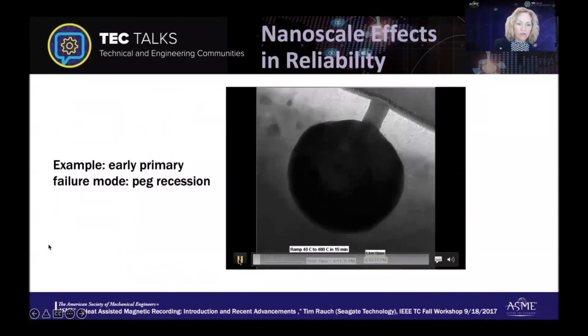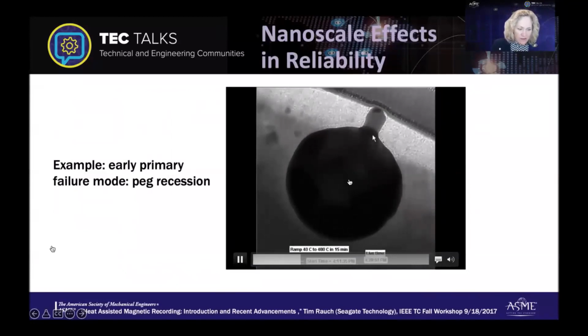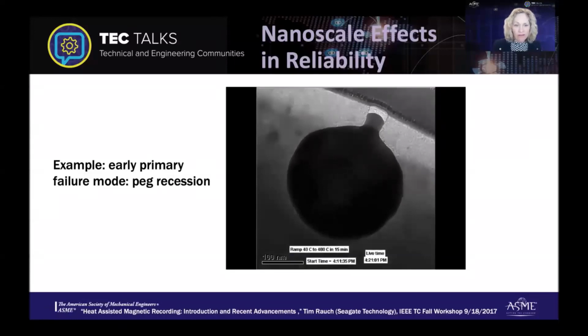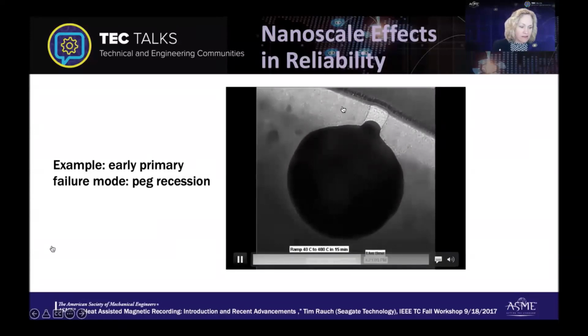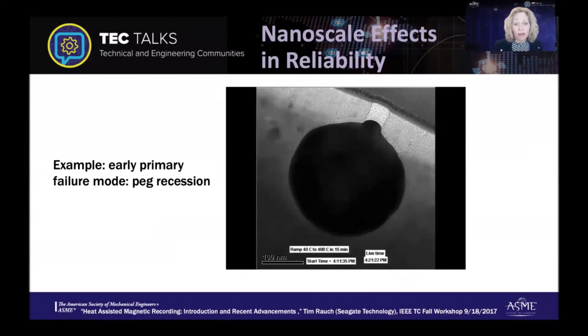We'll try that again. So you will see grains growing in the PEG, in the disc, and also the gold is densifying. And as the gold densifies, it wants to pull the PEG back into the disc. And you can see the PEG pulling away from the surface and being pulled into that disc. And because the surface plasmon effect is only a near field effect, once this PEG has retreated from the head surface, it is no longer within that tens of nanometers of the disc media, and the near field cannot reach the media anymore, and it fails to write any further. It's not heating that spot anymore. And this movie, really, with the tools of nanoscale technology, a transmission electron microscope, we are able to study this mechanism and come up with what was going on in this failure mode.